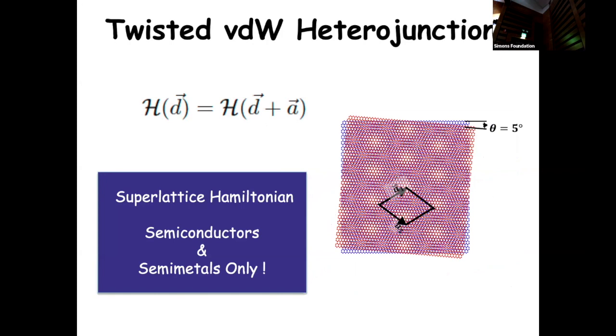Now here's a Moire superlattice made by a difference in twist angle or potentially a difference in lattice constant. Because all of the physics we're interested in occurs near these Brillouin zone corners, we can approximate the effect of modulation by the Moire pattern just by calculating the Hamiltonian and its dependence on stacking, which I call here D. Imagine rigidly moving one layer relative to another to vary the stacking. The dependence of the Hamiltonian on stacking, we only need to know it at the Brillouin zone corners.